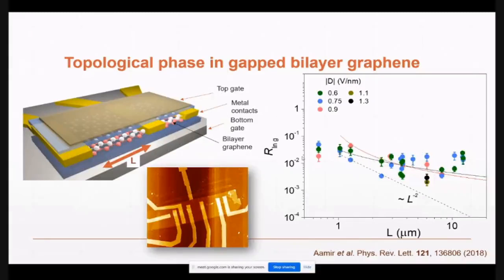We showed that when you gap out bilayer graphene, you actually see the current primarily along the edges, and that was shown through some noise measurements, which I will not go into. But these are very interesting aspects of graphene alone.